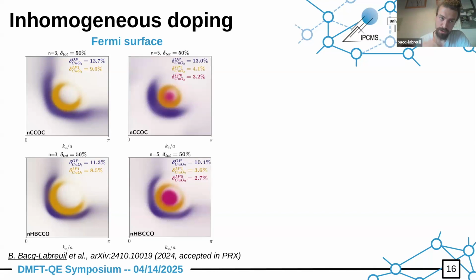This is already quite nice, but we can also look at what's happening in the 5-layer compound. Here we really see the coexistence of these arcs and also these pockets that we can already distinguish in the tri-layer compound, and an additional, even smaller pocket here, which corresponds to the innermost plane in the system. Of course, these pockets are perfectly symmetric with respect to the antiferromagnetic Brillouin zone, because the folding of these pockets comes from the antiferromagnetic fluctuations. This we can trace back to the physics of spin polarons and so on.